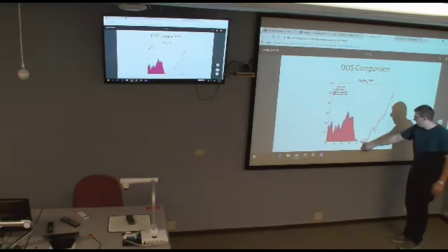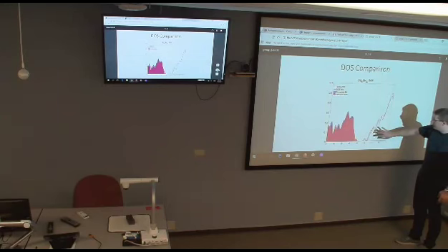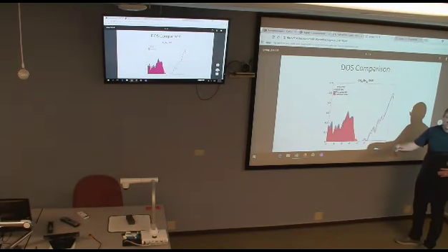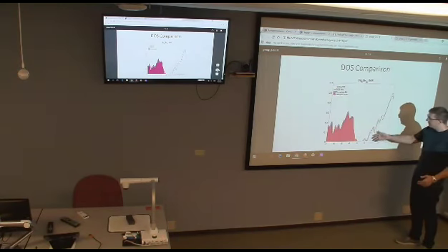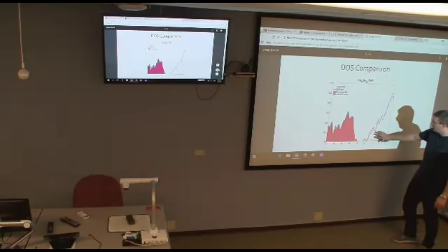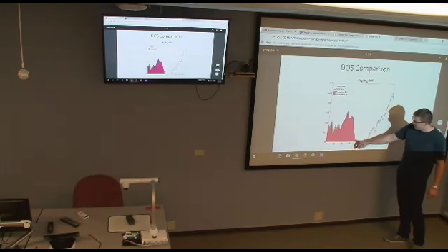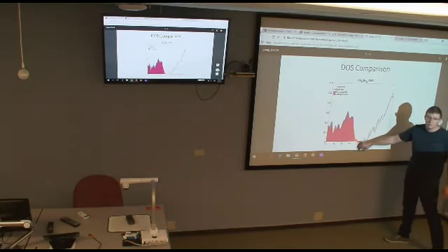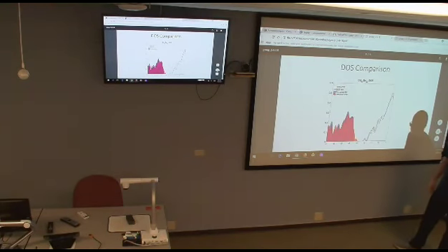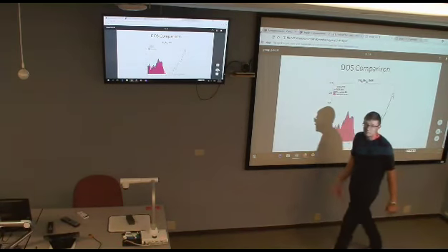Yeah, so primarily, and ideally that's what we want to see, because if we can have most of the unoccupied orbitals localized on the quantum dot themselves, then we're going to know that any type of excitation is going to try and maintain them on that quantum dot. Whereas the primary difference, like I mentioned with the other DOS, is this extension of the valence band pushing up closer to closing the band gap energy of the system. But again, the problem.